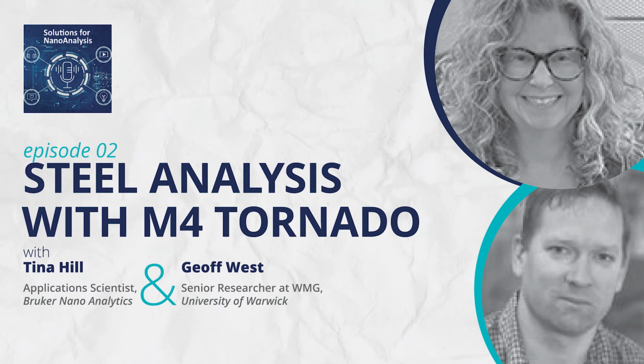Yes, definitely. So I'm curious to know, when you did look at those castings, and I'm not an expert in steels, so forgive the question if it's a little basic, but the segregations that you saw in those, are the grain sizes much different than, say, looking at the EPRI samples? So in a cast structure, you get different grain morphologies in different parts of the casting. It's about relating these different morphologies to where the segregation is occurring. And that's what is really important to understand. So knowing, let's say, grain size in those different regions? Grain size and shape. And shape. Because you get the elongated grains as well. So it's very useful for us to be able to relate those two things.